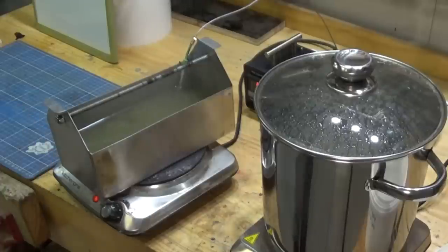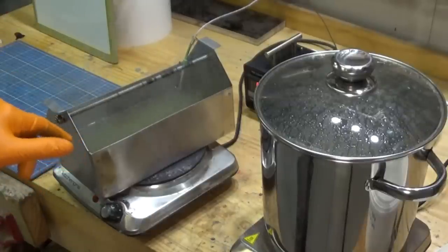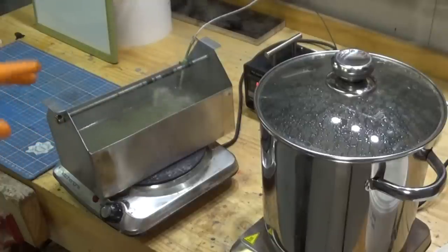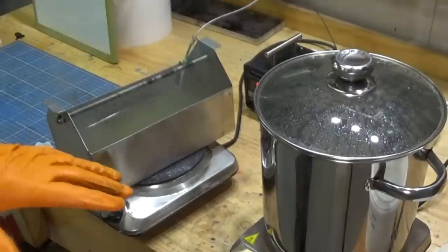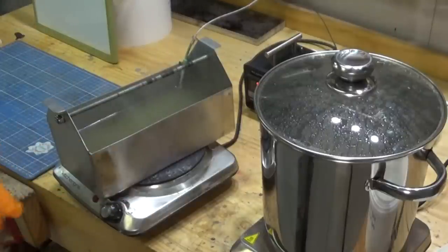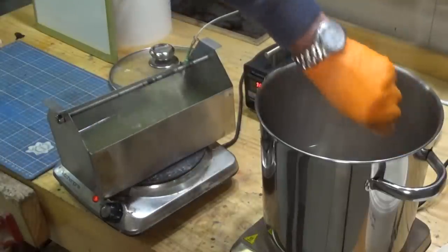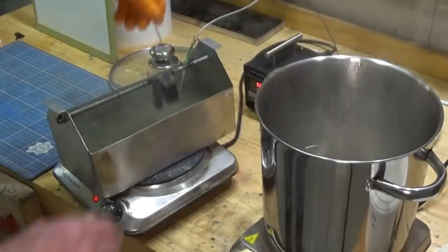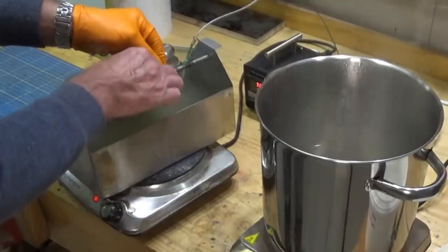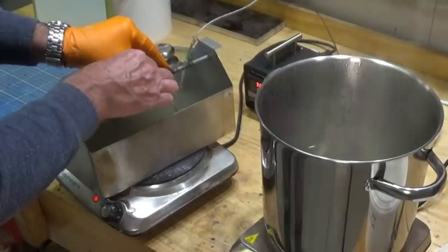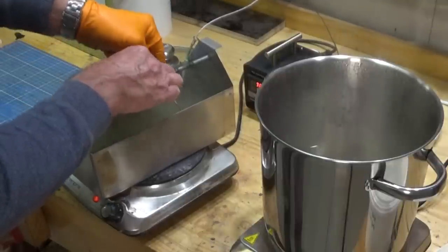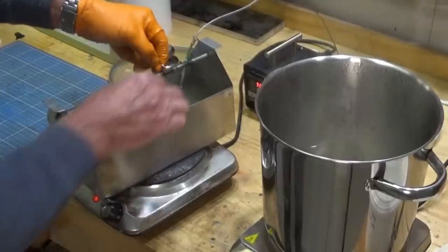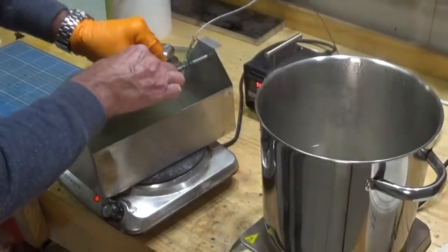Alright, so our parts have been in there for about a minute. So now they go straight into the parkerising tank. Now remember, I'm only doing parts 1 through 5, and part 6 is still in the cleaner. We're just going to dry that and then put the etch primer on one side. So straight out of the boiling water, straight into the parkerising solution. And ideally, you don't want that sitting on the bottom of the tank.